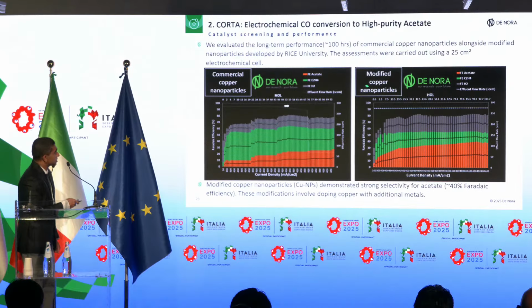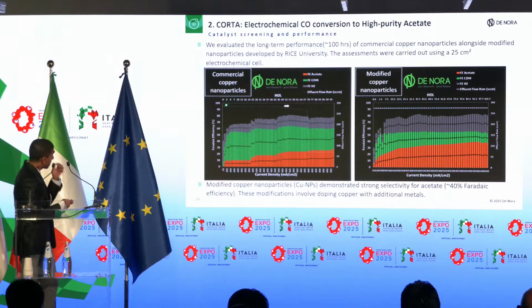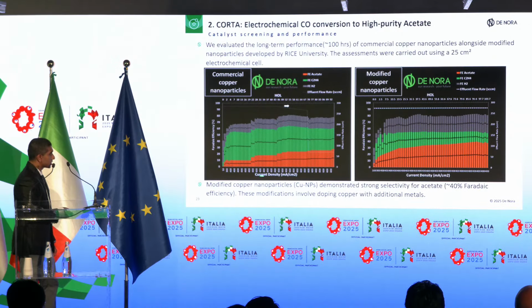So these are some results we obtained using commercial copper nanoparticles. The way to read this plot, the y-axis shows the Faraday efficiency, and the x-axis shows the current density. This data was collected at 400 milliamp per square centimeter current density, and on the top, you can see the hours online. Clearly, when we use commercial copper nanoparticles, we see acetate, which is shown in orange color, and the green color shows the ethylene, and gray color shows the hydrogen Faraday efficiency.